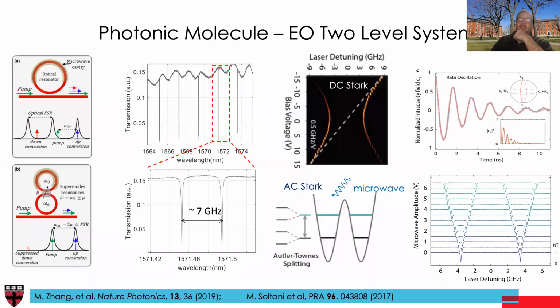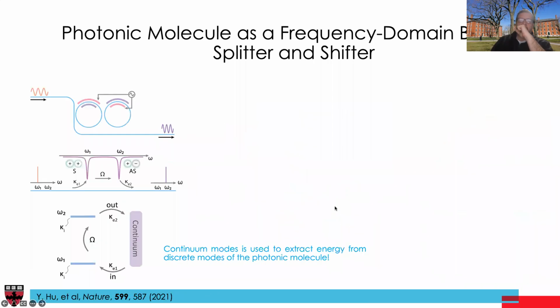But unfortunately, I mean, that works. We demonstrated that actually. But the problem is that you need to have pulsed RF, and these signals are about 10 gigahertz. Sometimes we go up to 30, and then if I want to have a pulsed RF source at about 10 gig, that means bandwidth needs to be much larger, and that just becomes really expensive, and we actually don't have one. But my student looked very carefully into this, and he realized a very interesting relationship between different rates, the rates of different processes that participate in this process.